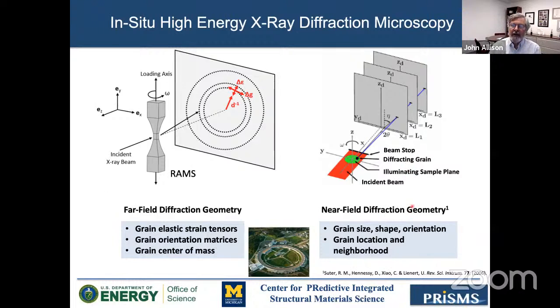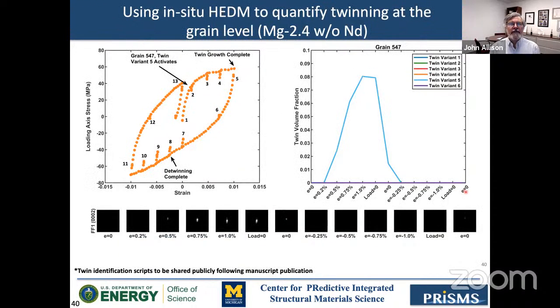But then they also have the capability to do near field diffraction, a technique developed by Bob Suter et al. at Carnegie Mellon, to do a very precise map of the grain size, shape, and orientation and grain location neighborhood. So we can really get a very detailed 3D map of the grains and their deformation. And so, as I said, Duncan took this very complicated challenge on to quantify twins in each grain.